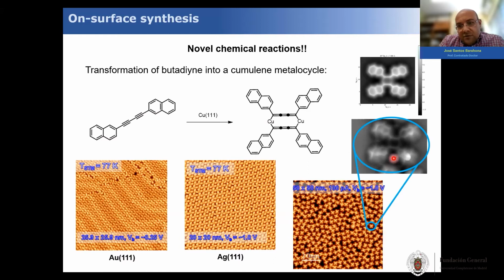And if we zoom in on them, we can see with the AFM what resembles a cycle in the middle and the naphthalenes on the outside, in the periphery. By running some calculations, we postulate this structure, which was then confirmed by DFT calculations. It is always needed to confirm our proposals by DFT calculation. This is very important. And this is the first reported case of a copper metallocycle like this, where you see a transformation from a butadiyne that converts into a cumulene.